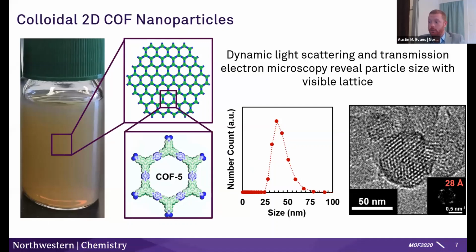But the TEM shows you that these are largely single crystalline, though they're very small. I'll point out that the size of these particles is actually commensurate with the size that most folks were obtaining in their polycrystalline aggregates via some Scherrer analysis or some X-ray diffraction interpretation. So this size is pretty consistent with what we would have obtained in a polycrystalline powder, but now they're stabilized as single crystals.